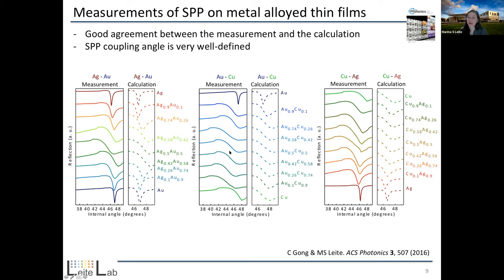So this requires a little bit more optimization with respect to the thickness of these films, as well as the roughness of the film. So basically on the fabrication step. But I think our goal here was not necessarily to show an optimized dip in reflection, but actually how we can tune that. And then for copper and silver, again, we see that the system doesn't behave as well.